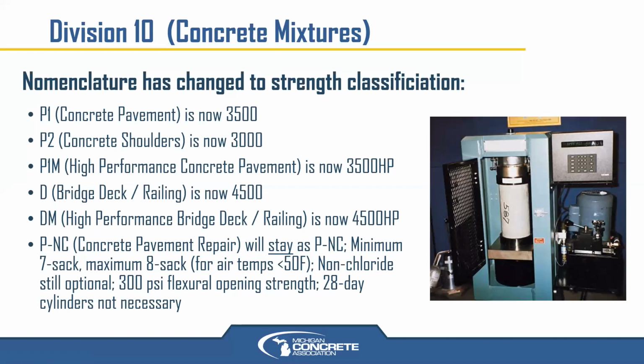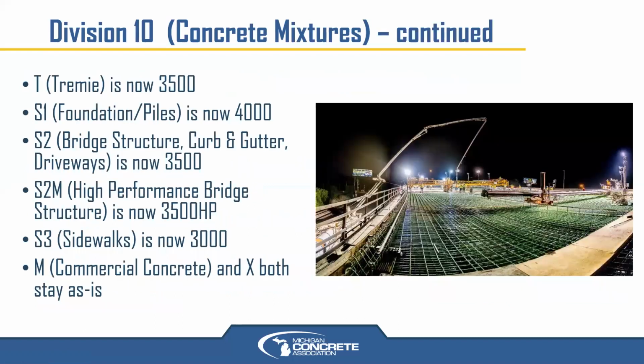If you choose to use a P1 or P1M for your pavement repair project, you still go with that 550 PSI opening strength like you do on a new pavement. But if you want the higher early repairs with P-NC, then it's a 300 PSI flex. Your Tremie mixes are now essentially the same as your S2 and P1 because they're just based solely on strength. If there are any other different requirements for a Tremie mix, as far as aggregates, admixtures, water content, etc., then the concrete producer would have to obviously note that with their mix design submittals, which is something we'll talk about on Thursday morning when you tune in at 10 a.m. We'll talk about JMF submittals and mix designs.